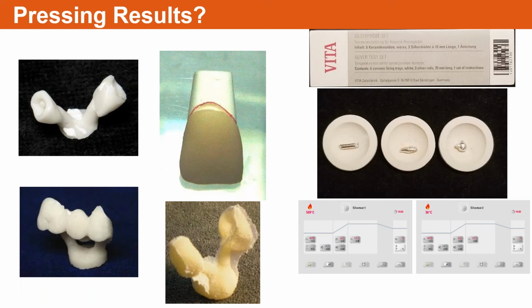Silver test is an easy, more accurate way to check your furnace. The VITA furnaces all have built-in cycles for silver test. The first temperature is approximately 10 degrees lower than the melt point of silver. The silver itself will start to swell up. And then add another 10 degrees for the second test. That additional 10 degrees should ball up, completely melt your silver, and then you know it's working.